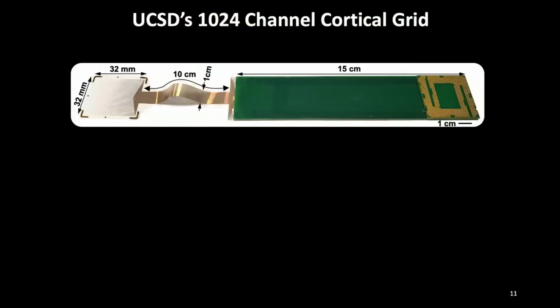So at UCSD, we used thin film technology. This is microfabrication techniques used for display screens, for instance, to make devices that have large area coverage and large connectorization to separate the electrode in the sterile medium from the non-sterile medium where we are doing the acquisition electronics. And the version that we're looking at is a 1024 channel cortical grid with 1 millimeter spacing between the contacts. So this covers 3.2 by 3.2 centimeters.